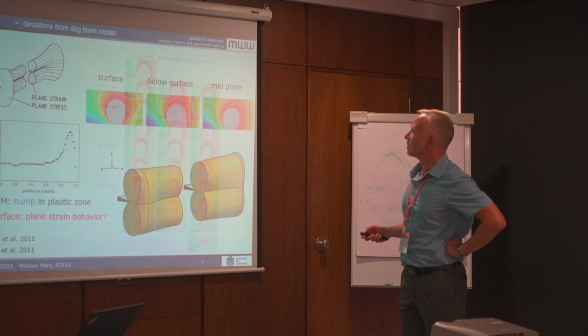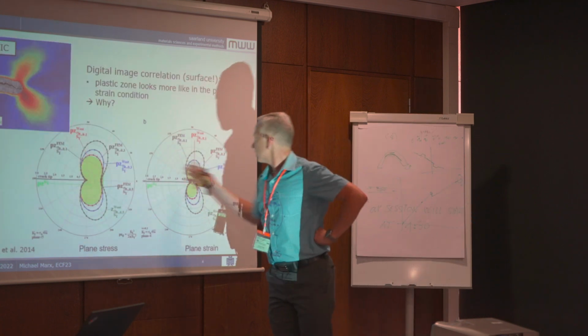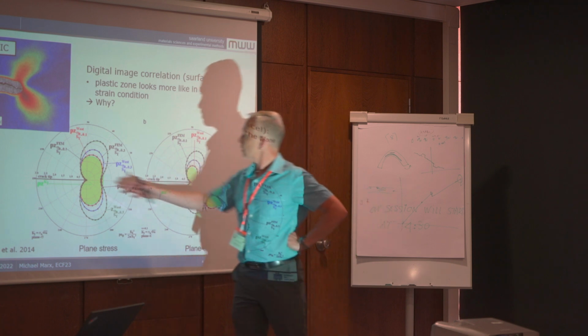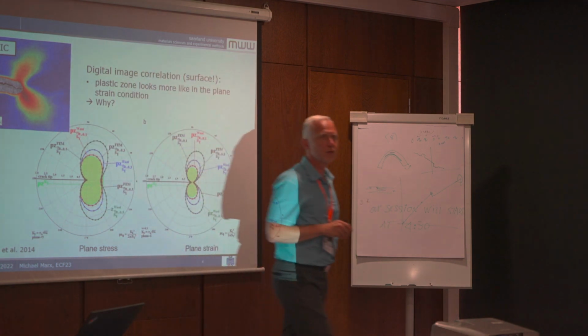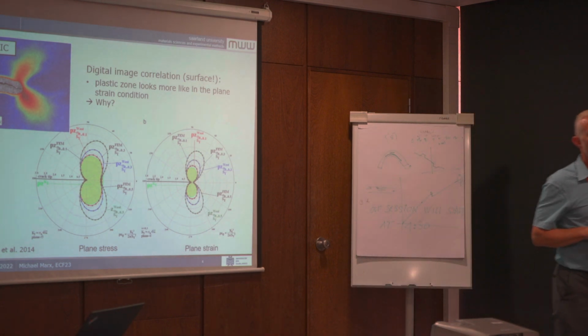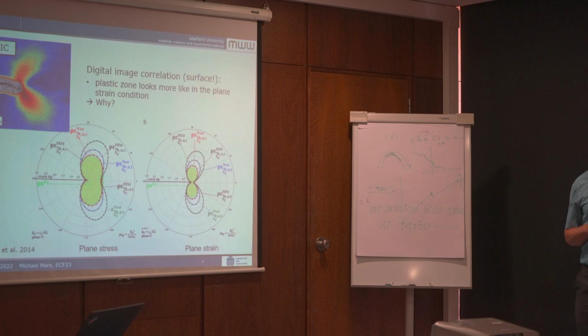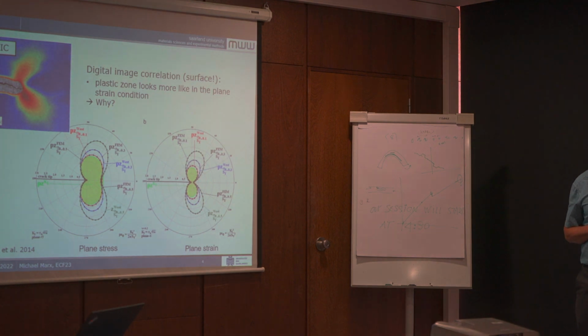This is maybe the same as I have shown at the beginning. Here it's also different for the plane strain and the plane stress, and this is what you also get by the simulation measurements, not only from the X-ray measurements. Yes. So there is something. Is it possible that with the X-ray measurements, you make some kind of average, whereas in the simulation you just look at the real surface? Sure, we will have some average because we do not get our information from a thin layer, because of the absorption, and absorption happens while the X-rays go through the material.